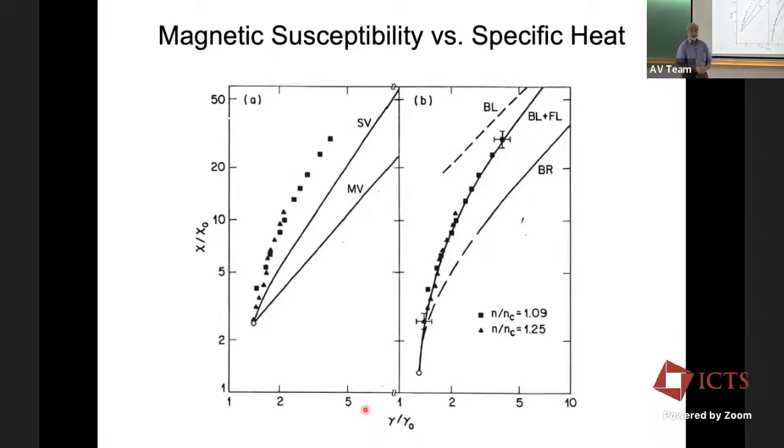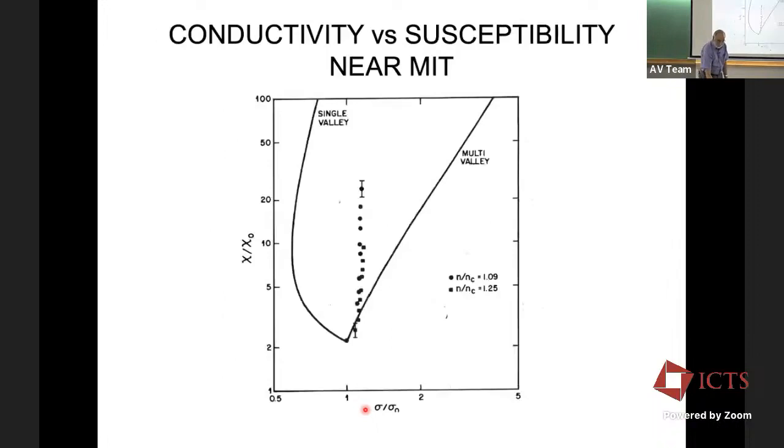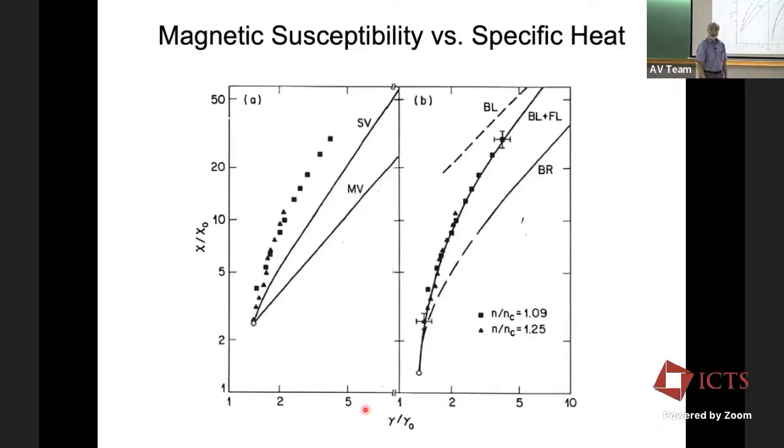It's really hard to measure specific heat because specific heat is going down as you go down in temperature. But he did a very good job. And we have a whole Physical Review letter on that, showing that the specific heat is not going linear in temperature, it's going as a sublinear power of temperature. There's very good evidence for that. In fact, it will change a little bit, yes. Right, and we'll have to take that into account when someone measures the specific heat of phosphorus and boron doped silicon.